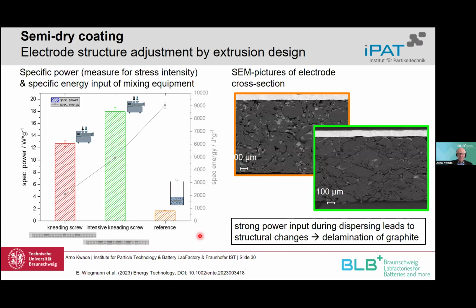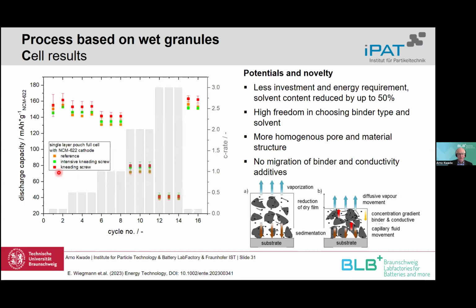And this also changes the structure, because with a high intensity kneading process, we also delaminate the graphite, which we don't do in the reference, and also almost not with the normal kneading screw. And at the end, if we come to the performance, you see that the only kneading screw gives us the best results. So we're very pleased with that with this new process, we get really good performance.